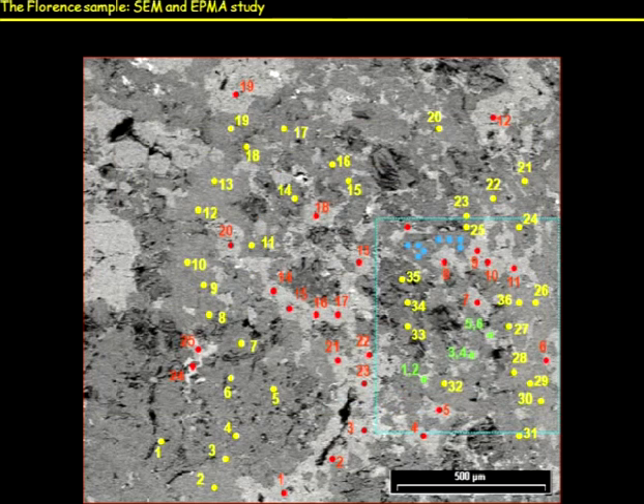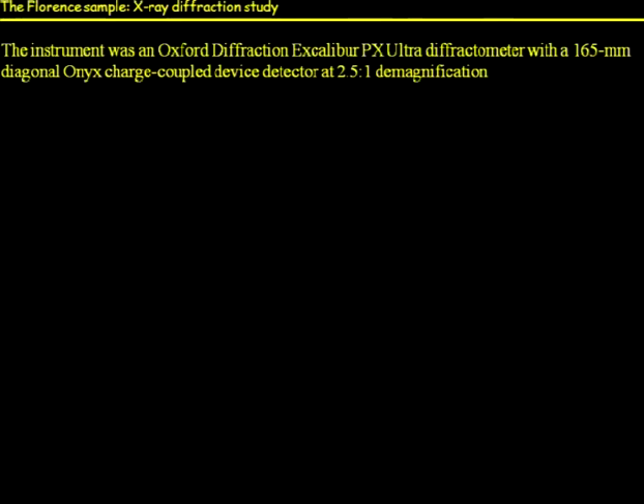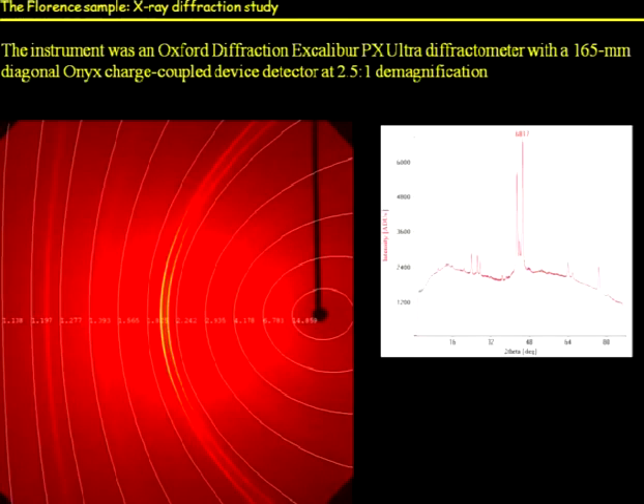What I had to do, in addition, was try to extract the crystals by hand, picking, and try to obtain an X-ray diffraction investigation. So I was able to extract the grains. It was a very hard work, believe me. Anyway, when I extracted the grains, I immediately ran to the lab in another building to make an X-ray diffraction investigation. The results were very disappointing at the beginning, because you can see that the crystal does not diffract as a single crystal. You can see not single spots, but diffraction cones. Anyway, it is not important because we can easily convert it into a conventional diffraction pattern, something like this, where you can see the sharp diffraction peaks.